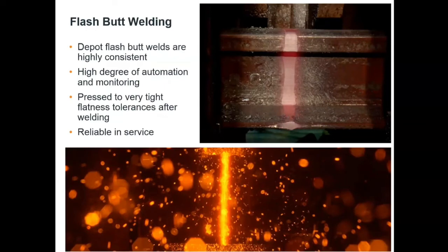What you can do in the depot is any thermal distortion you've got from the high heat input, we can press that. We've got a press. We can correct that, and we've got an auto grinder to grind flush the running surface, so the rail doesn't see any difference. The wheel doesn't see any difference. It just sees parent metal, ground smooth, a very, very reliable jointing method.